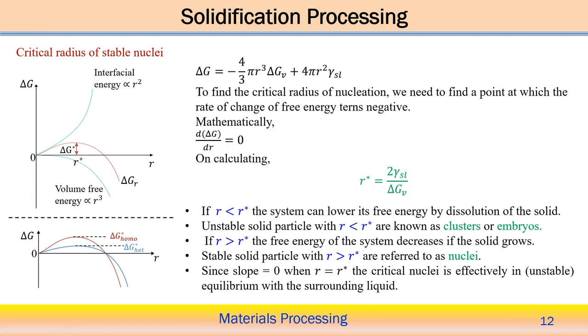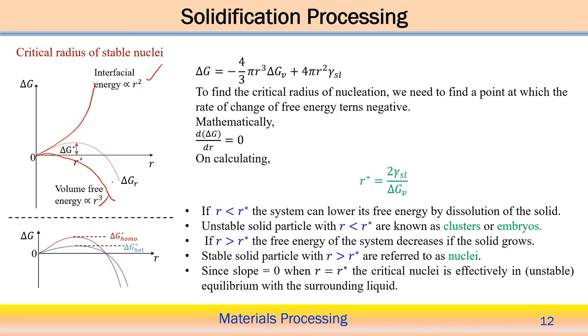Here you see this represents the interfacial energy, and this is the volume free energy. The interfacial energy is proportional to r squared because it depends on the surface area, and the volume free energy depends on the volume, proportional to r cubed. So r is the size of the particle, and we see delta G at a particular radius as a function of r. Delta G consists of the volume free energy and the surface free energy. This is the curve of it.